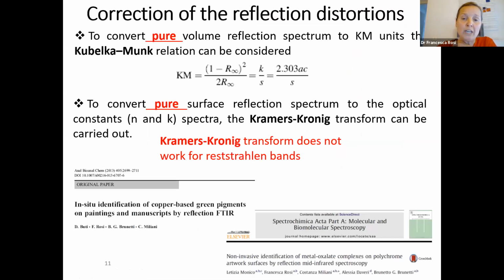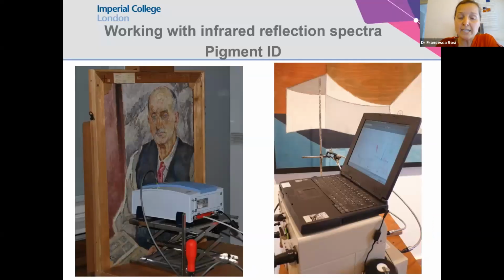From a theoretical point of view, we can correct this kind of spectra, obtaining profiles that are more traditional and easier to interpret. As a matter of fact, when we work with the surface of artwork, we have both contributions to the reflectance, which means they are present in variable and unknown proportion. In our experience, it is better not to convert, in order to avoid further distortion and misleading conclusions. In this webinar, I'd like to show you what information can be achieved by working with the raw reflectance spectra.